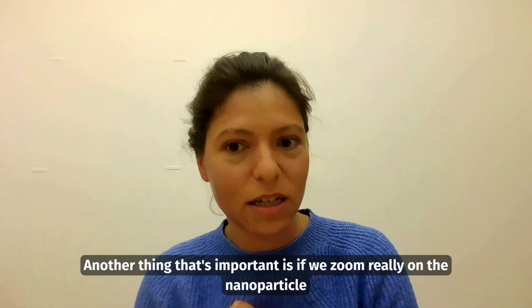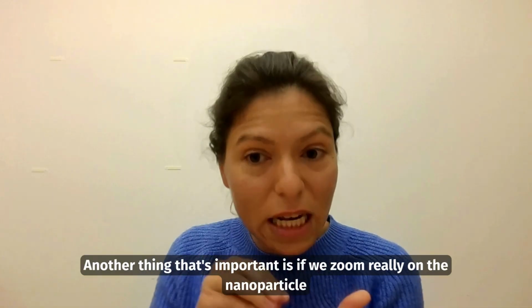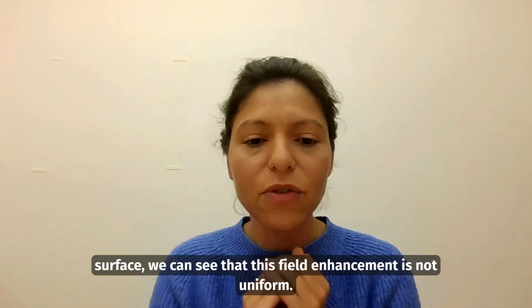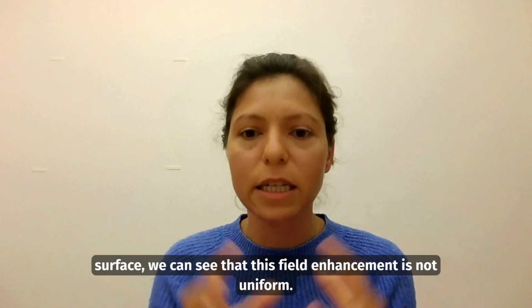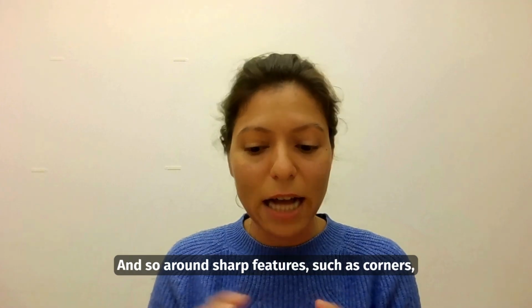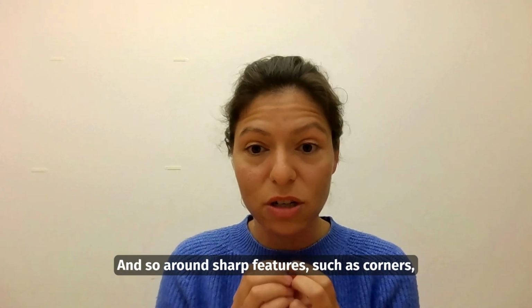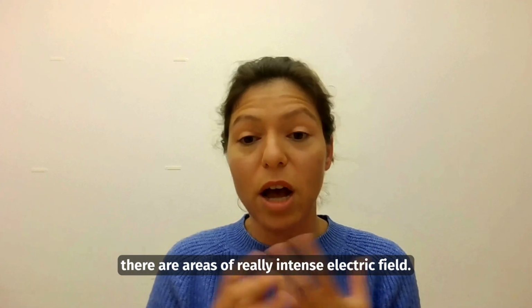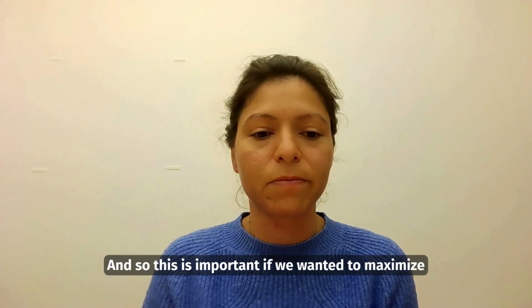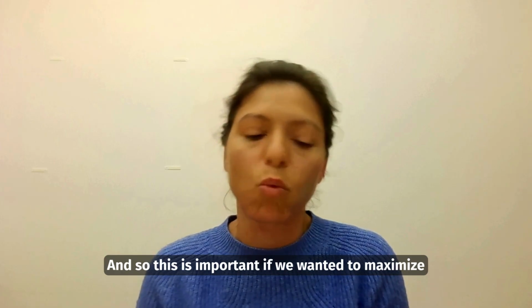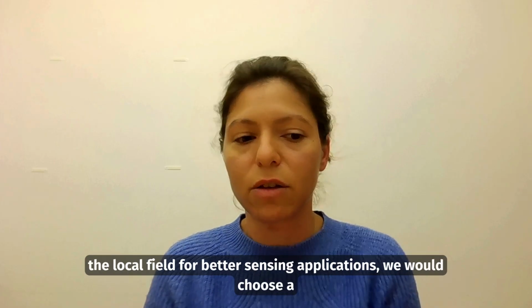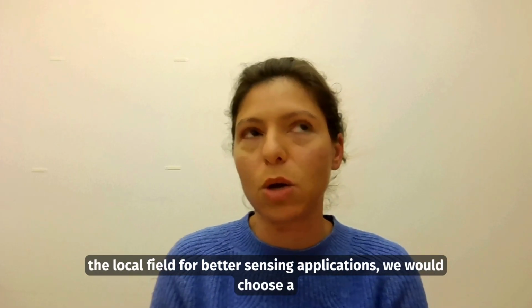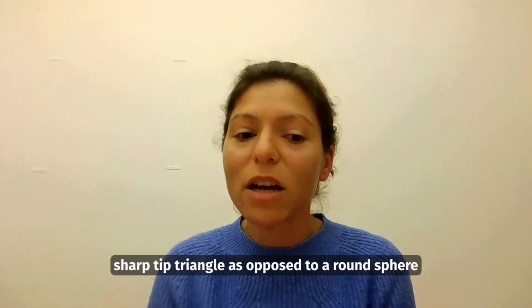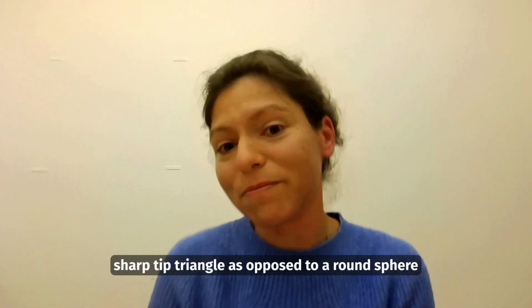Another thing that's important is if we zoom in on the nanoparticle surface, we can see that this field enhancement is not uniform. And so around sharp features, such as corners, there are areas of really intense electric field. And so this is important. If we wanted to maximize the local field for better sensing applications, we would choose a sharp tip triangle as opposed to a round sphere.